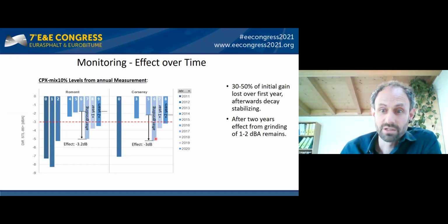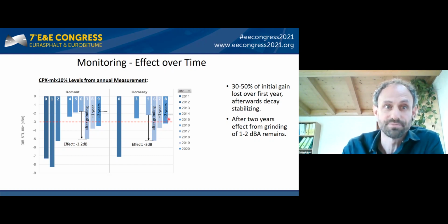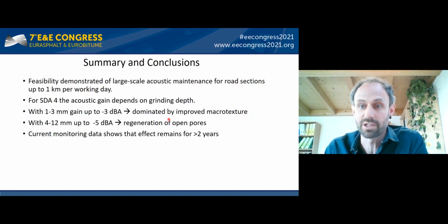In the first year, we observed a loss of 30 to 50% of the initial gain. In the second year, this decay decreased, and we still measured 1 to 2 dB of remaining effect from grinding compared to the level before, still below or close to the 3 dB margin. With this, I come to my summary and conclusions.